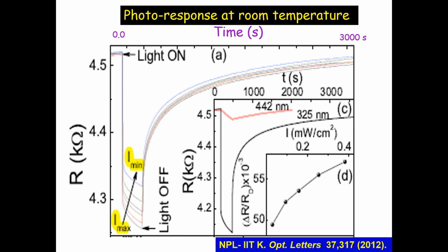If I use a helium cadmium laser, which has two lines, 442 nanometers and 325 nanometers, there is very little change with 442, and this particular UV line 325, which is 10 times weaker in the laser, you see this large effect. So it's only UV sensitive.